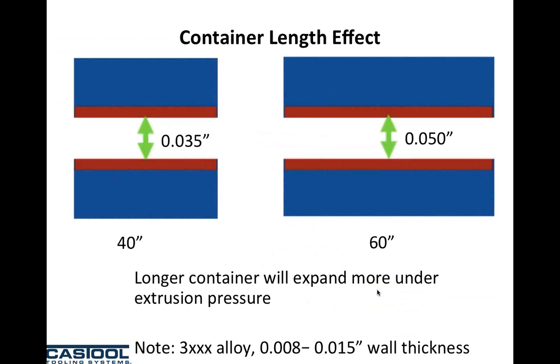And when we look at the dummy block and the container, we work this into our calculations. So we may allow somewhere 20 to 30 thou clearance at room temperature between the dummy block and the container. We may have about 30 to 35 thou expansion in the dummy block during operation, and we allow for about 35 thou deflection of the container bore during extrusion, and everything is fine. What happens if we suddenly go to a 60-inch container?